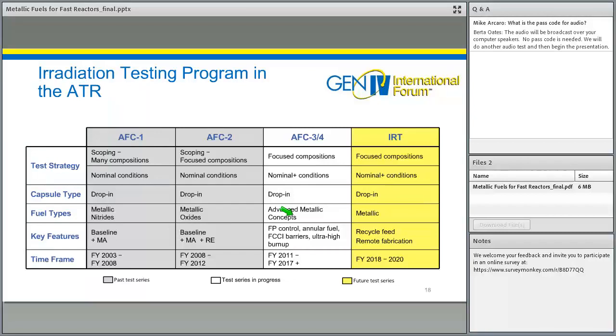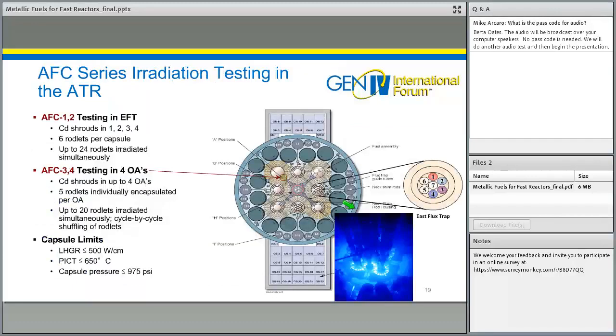So we're in the middle of the 3-4 test series now, and hopefully next year we'll be starting a new experiment called IRT. So this is the integrated recycle test. And this is a test we're doing in collaboration with the Korea Atomic Energy Research Institute, specifically looking at performance effects associated with not simulated but genuine recycled fuel. So part of this project is an actual recycle of fuel, taking that recycle feed, using it to fabricate metallic fuel in the hot cell, and then introducing it back into the reactor, in this case ATR, to determine how it performs. That should be tested starting next year.